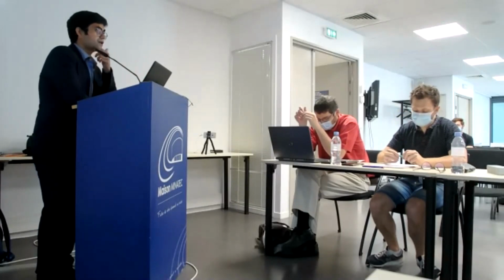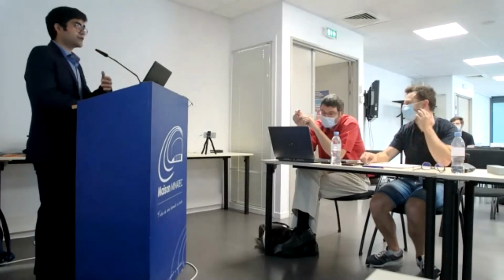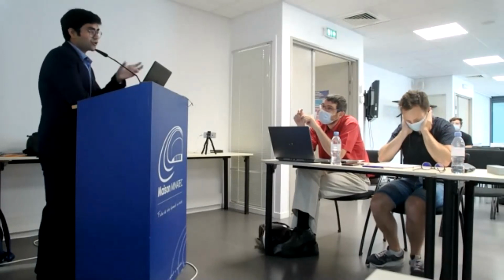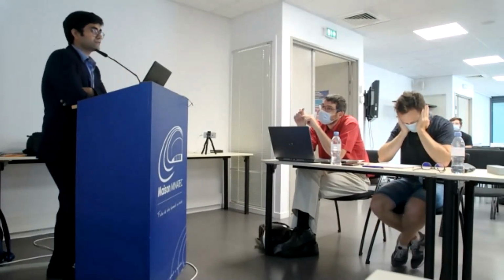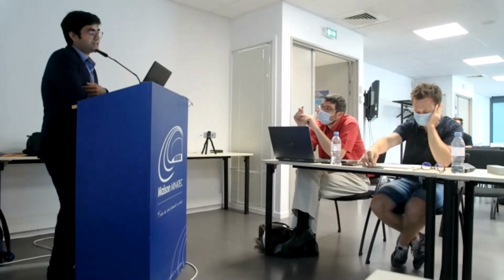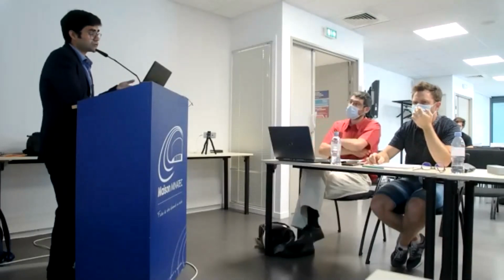True. Compared to welding, what we have observed is that welding has very little strain rate as reported in the literature, and compared to that, in L-PBF, based on our small empirical calculation, we found that it is quite high. And to my feeling, this can play a role, and it also needs to be studied in detail, I think.